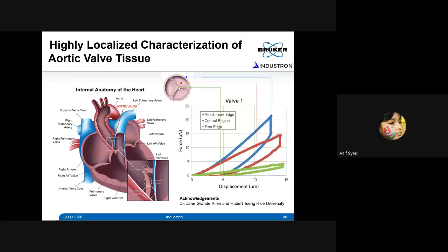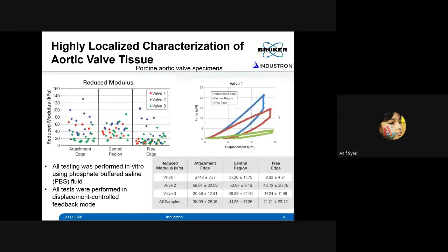That's what you see on this load displacement curve. You can readily see that at the edge, for a given interpenetration, let's say 10 micron, you require more load to penetrate 10 micron or higher depths. So the edges are stiffer compared to the middle and the end. This is how it's supposed to be. At the middle, it is less stiff than the edge, and at the end it is very soft compared to the rest of the region. We can do a number of tests, it's very repeatable, and then you can see the properties in terms of modulus.